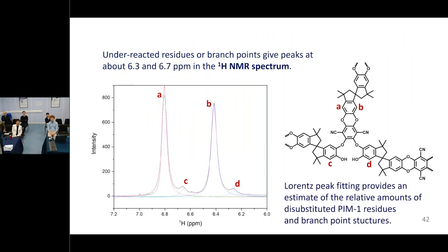We can actually see when that's happening if we look in detail very carefully at the proton NMR, because you get some little peaks beside the main peaks for some of these hydrogens, which we attribute to an unreacted or branched one. And we can do Lorentzian peak fitting to come up with a rough degree of branching.